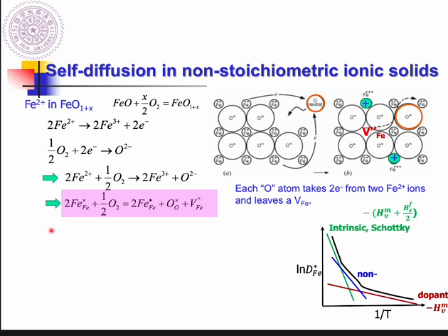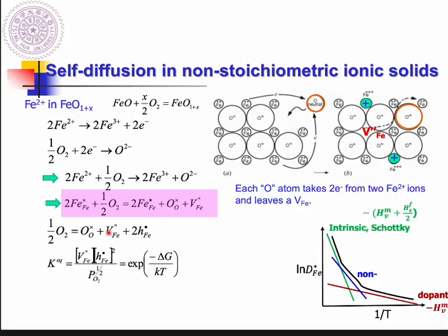So once you have these equations, then you can formulate the equilibrium constant K. This times this squared times this, neutral, squared, holds to 2 and vacancy, divided by here. So the partial pressure of oxygen, and the order is 1 divided by 2. This equation gives the free energy.